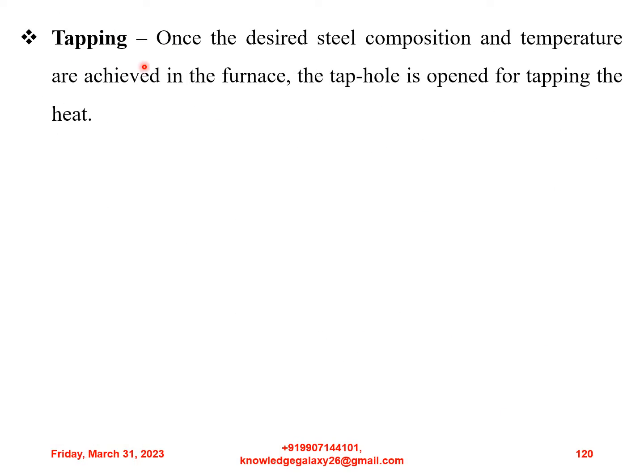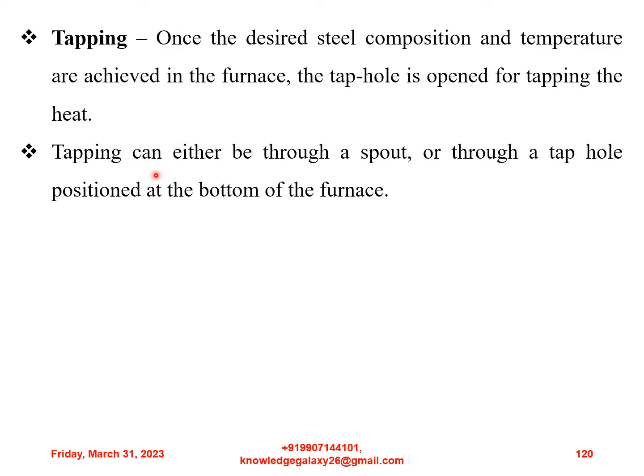So the next operation is tapping. Once the desired steel composition and temperature are achieved in the furnace, the tap hole is opened for tapping the heat. Tapping can either be through a spout or through a tap hole positioned at the bottom of the furnace. In case of spout tapping, the furnace is tilted and the steel pours into a ladle for transfer to the next batch operation, normally a ladle furnace.